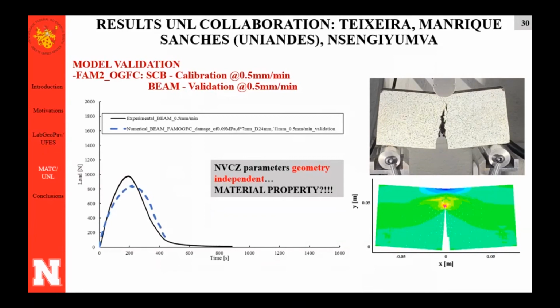Then we took the same parameters that we calibrated for one geometry, and we tried to see, can I use the same parameters if I change the test geometry? And we also got a fair prediction of the 3-point bending beam test with the same parameters. So the nonlinear viscoelastic parameters were geometry independent. So are we talking now about a material property? It's not a parameter anymore. It's not geometry dependent. So that is one thing that we got, and we're still working on the analysis of this data.